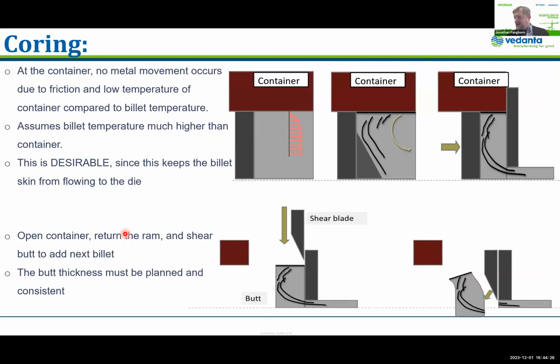Moving on here to coring. Your container is set at a temperature, hopefully well below your billet temperature, to arrest the flow of the surface layer, the segregation layer, or as it is roughly termed, billet skin that is on the surface. At the container surface, you really have almost zero metal flow, and then towards the middle, of course, the billet is moving much more easily.